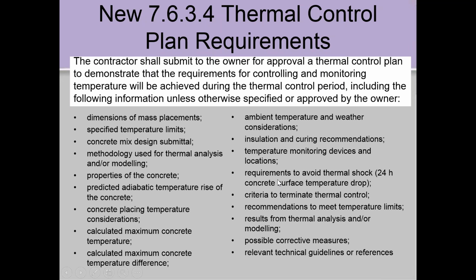including avoiding thermal shock. A lot of times winter concrete, when they remove the forms and it's really cold out, you're going from a hot concrete to like a minus temperature exposure, and it can cause thermal shock, which just causes thermal cracking. So it could be weather-related thermal cracking.